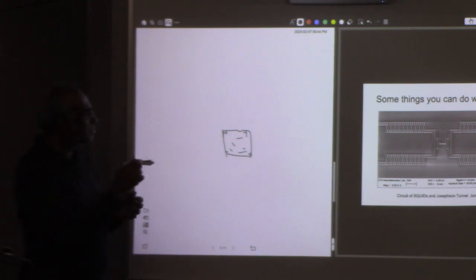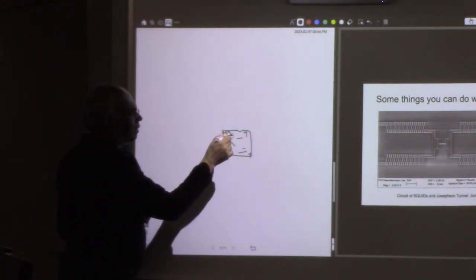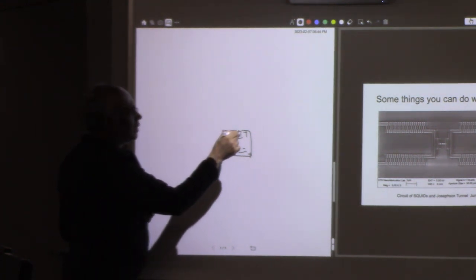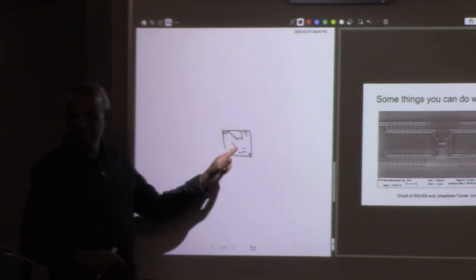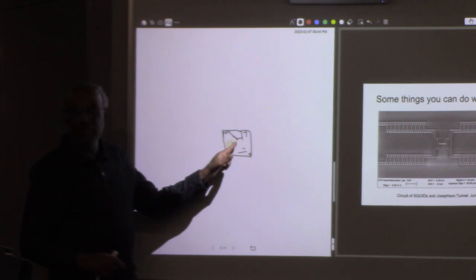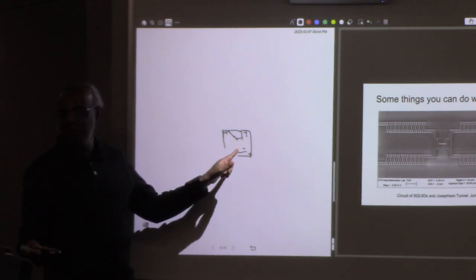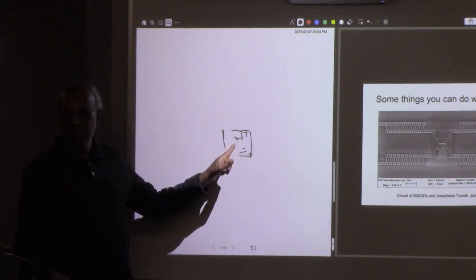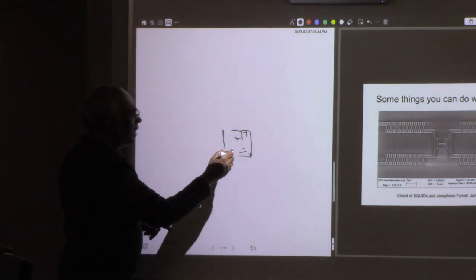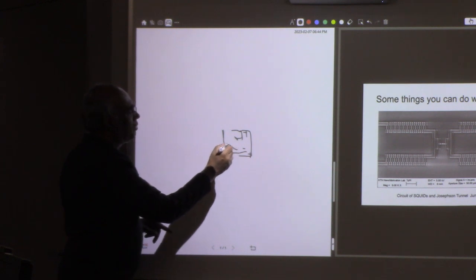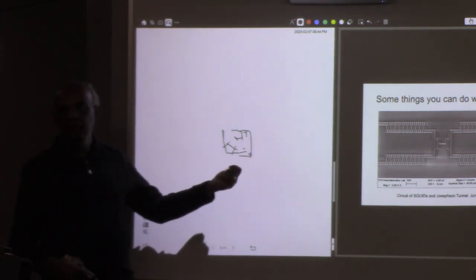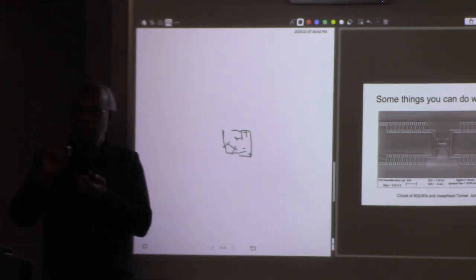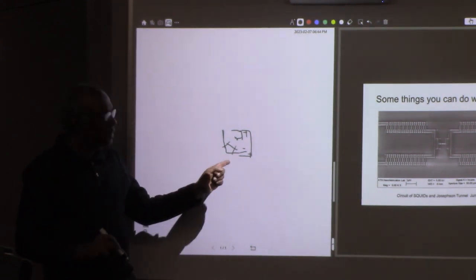That you can program so that I can write one like this and another one like this, so that I can connect with the nanotube. But you don't see the nanotube because it's already covered with the photoresist, right? So it's a kind of guesswork. So then I can make another one like this. That's why we have several of these. I can write. This is what we call the E-beam writing. So that with the E-beam you can raster your beam and make that.